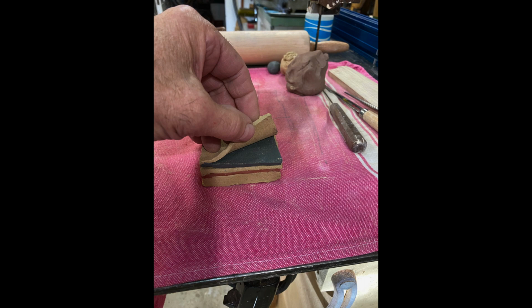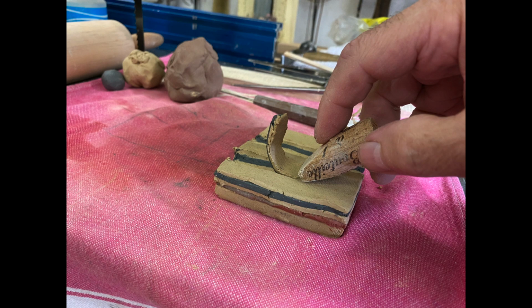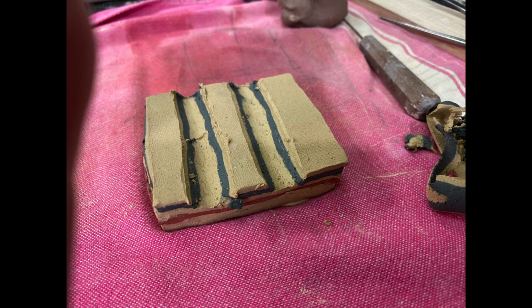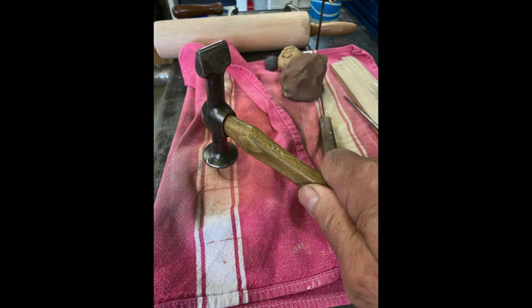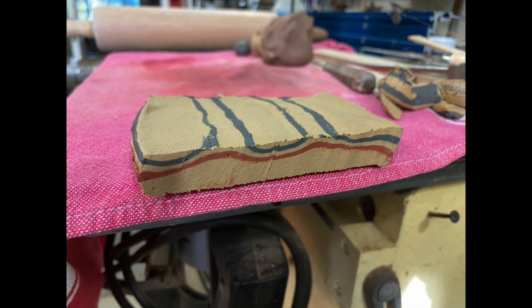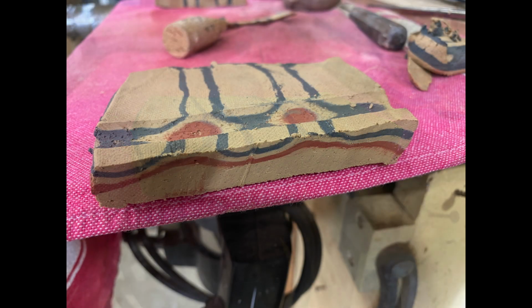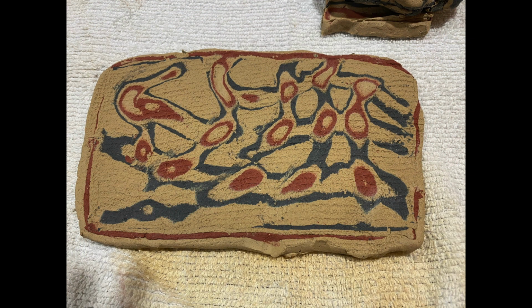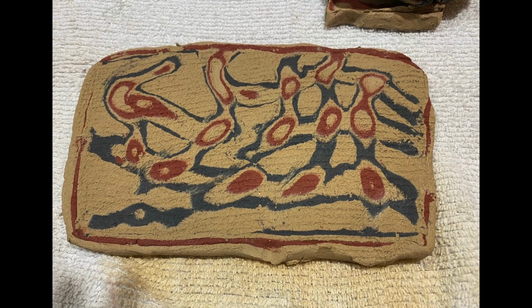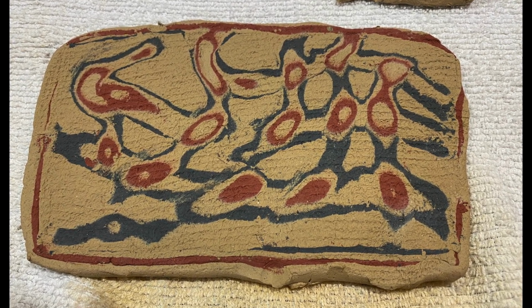First, the layers. I cut down 3 layers here. In the billet, I cut many parallel channels. The flattening process pushes high areas down, but it also lets the channels fill with raised up lower layers. Now, I cut down again as deep as the 3rd layer. After flattening, you can see the lower contrasting red layer exposed, mostly at the intersections. It forms this bullseye or dot in a regular pattern.